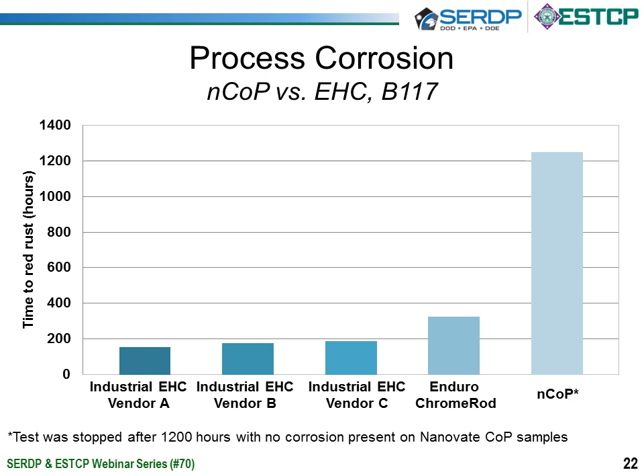So there's a lot of work that went into the cobalt phosphorus development to date. I won't go through all the property comparisons, but one in particular that I'll just mention today is regarding the corrosion. This is a salt spray corrosion compared to hard chrome. And this is an area where we see significant improvement. We've tested it against a number of electrolytic hard chrome vendors, and we see that the time to red rust with the cobalt phos is significantly higher, going from about 200 hours to over 1,200. So this is really one of the areas where it performs very well.